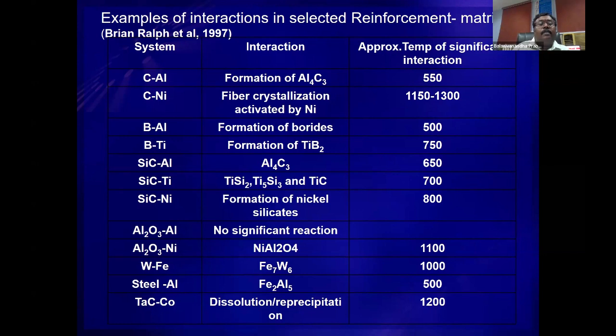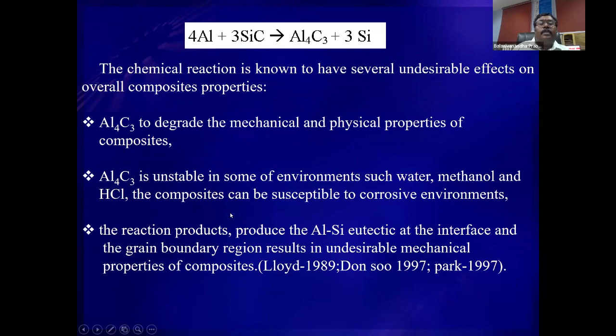So we have also extensively studied this Al4C3 formation, which is formed by aluminum and silicon carbide. Silicon carbide separates into Si and C, the C reacts with the Al and forms Al4C3, and 3 silicon is left, and the silicon goes into the nearby matrix material and modifies the chemical composition of the aluminum alloy also. This separation takes place only on the surface of the silicon carbide. So Al4C3 degrades the mechanical properties as well as physical properties.